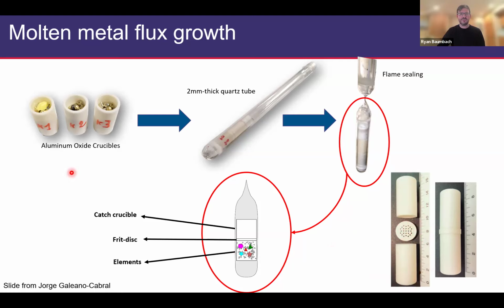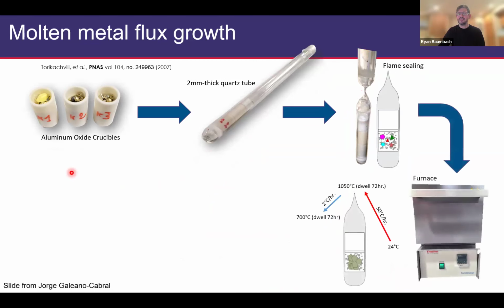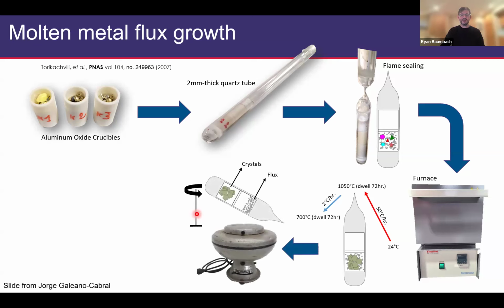So we have our ampoule. We can take this thing now, seal it, and place it inside of any furnace that we like, right? Take it through a heating schedule that goes into the melt and then slowly decreases temperature such that we cross one of these solidification boundaries. When we're done, we want to take this out of the furnace while it's still hot, so that the flux is still in its liquid state. We then invert the crucible, place it inside of a centrifuge, and spin it hard. The result is that the flux will pass through the fritted disc and crystals will remain in the growth crucible.